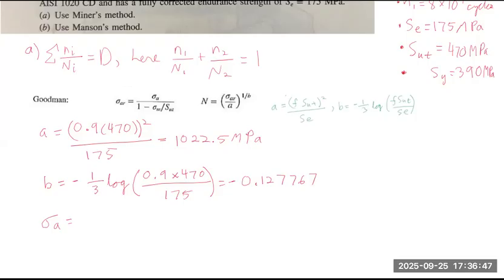So we amplify the nominal alternating stress by Kf to reflect the localized cyclic stress at the notch root. This is critical in fatigue analysis using methods like SN curves, which is the stress life method, modified Goodman, Gerber, or Soderberg diagrams. Multiply sigma A by Kf to reflect actual fatigue damage potential at stress risers.